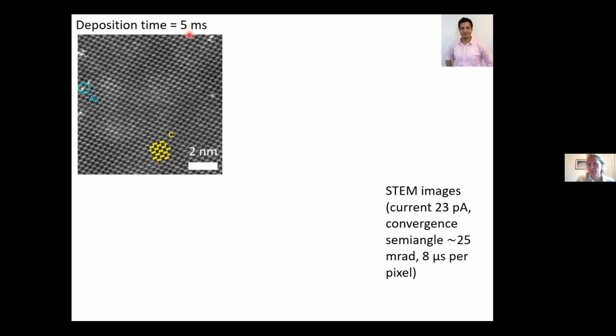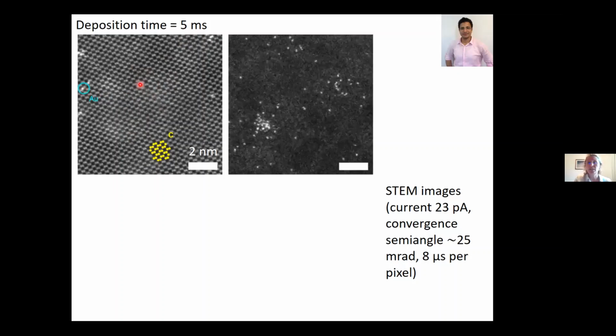So this is a 5 millisecond deposition. And you can actually see here, depending on the angle that we image at or the focus that we have, you can focus just more onto the BDD itself, or you can focus onto the gold. Here you can actually see really nicely, so this is the aberration corrected transmission electron microscope, the atomic resolution of the BDD background. But you can also start to see, after 5 milliseconds deposition, these single atoms on the surface. Not only do we see single atoms, but we also see evidence of what we've called atom clusters. They're atoms that have come together, but they've not formed themselves into a crystalline structure.